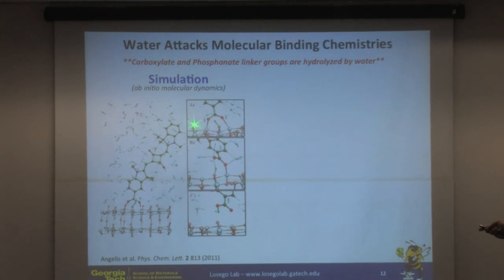These are all these water molecules running around in an aqueous environment. And when they looked at this, eventually you get hydrolytic attack of one of these attachment chemistries, which can be a problem. But even in the case of a multi-dentate binding of a molecule, so in this case we have two binding sites, you might expect that this might reattach at some point before this one detaches. The problem they found in this particular simulation study was that once this detaches, the water molecules start to surround it and prevent it from reattaching to the surface. This makes it even more unstable, and eventually it gives sufficient time that another water molecule can attack the second site and desorb the molecule.